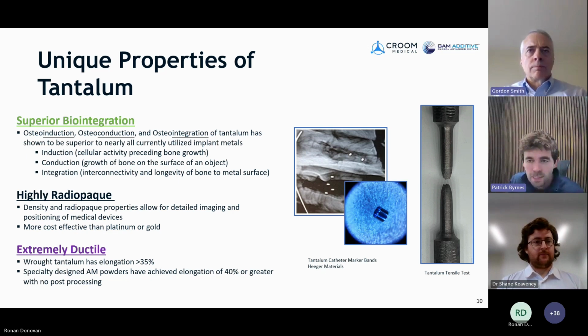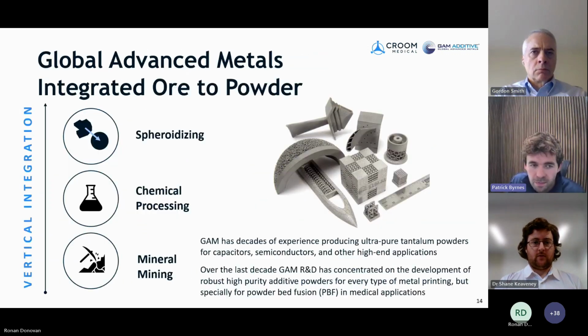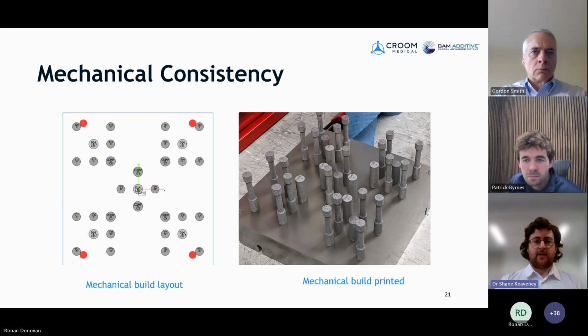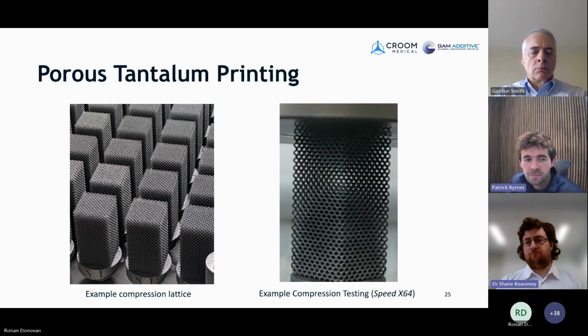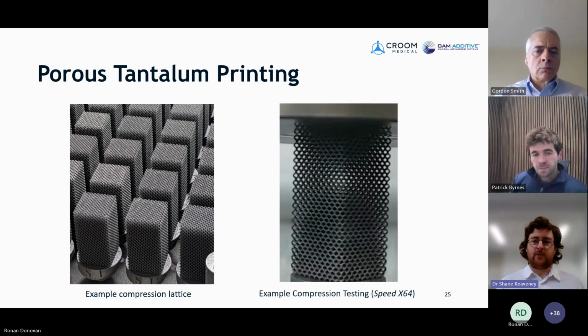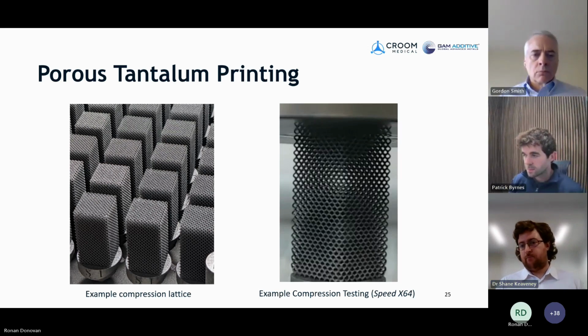It seems like porous titanium Ti64 has very similar properties to porous tantalum. What makes tantalum more beneficial than titanium? Yeah, again, if I go to this slide here, I think that's for us one of the key pieces. It's this failure mechanism. If you look in the literature, you might see a little bit around how titanium 6-4 fails. It hasn't got the same level of ductility as tantalum. And what that really means is that there's a larger amount of plastic deformation, i.e. the material can deform without failing in a plastic mode, which is one big benefit.